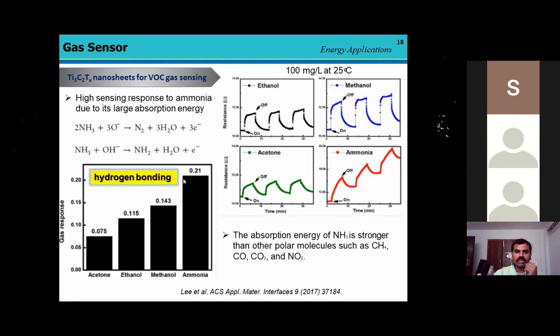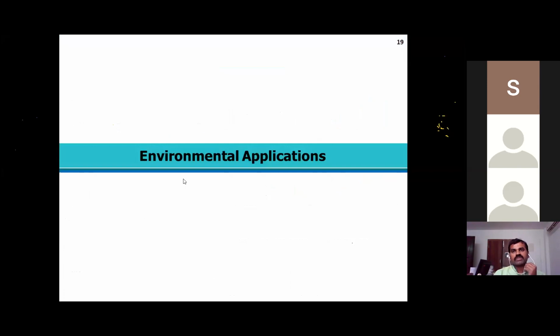And among these, ammonia has higher sensing response due to large adsorption energy, which was confirmed by DFT studies also. The adsorption energy of ammonia is stronger than the other molecules, such as methane, carbon monoxide, carbon dioxide, and nitrogen dioxide at room temperature. Besides, there are a lot of applications focused on lithium-ion batteries, fuel cell application, and photon up-conversion reactions using MXene-based materials.